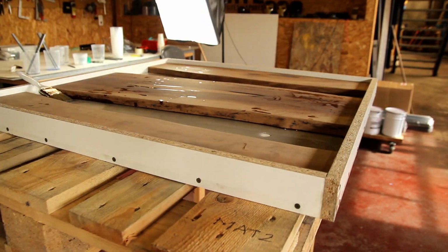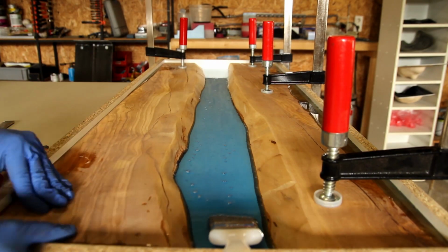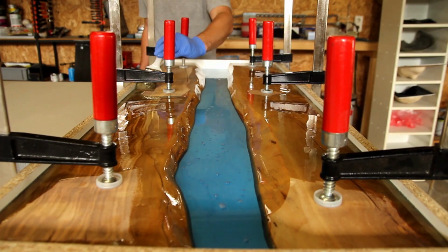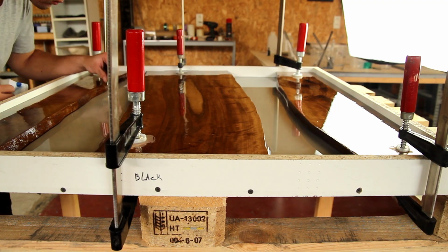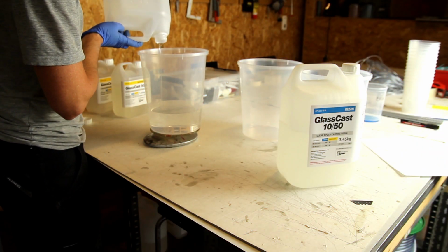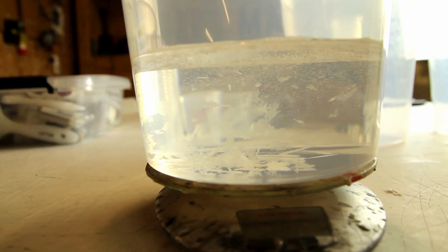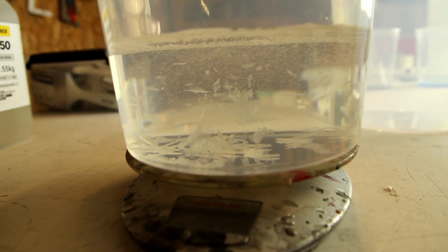The measurements are on the Glass Cast tins. It's 100 by 45 if you do it by weight, and I would strongly advise you to do it by weight. So you add 100 grams of the A and then 45 grams of B.